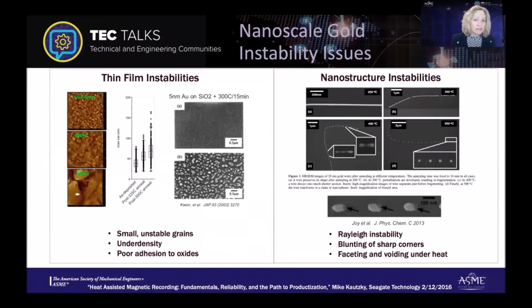We also had to bring in some of the other reliability issues that people were seeing with nanoscale gold and its different behavior, because at this 400 C, gold should not be melting. So what's happening with these phenomena? We're seeing grain growth, which is certainly one of the problems we were having. People were seeing poor adhesion to oxides for these thin gold films. And with nanoscale gold structures, people were seeing nanoscale structure instabilities. And some of this is with everything being a surface, those sharp corners, it's easier for atoms at those corners to be pulled off or to minimize energy in those rounder shapes.